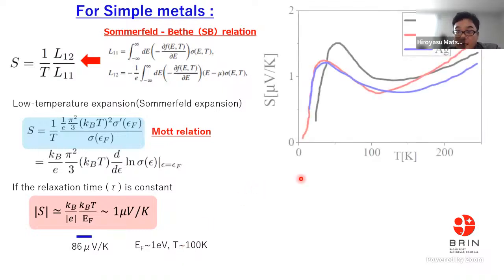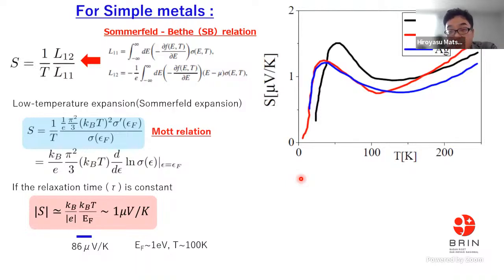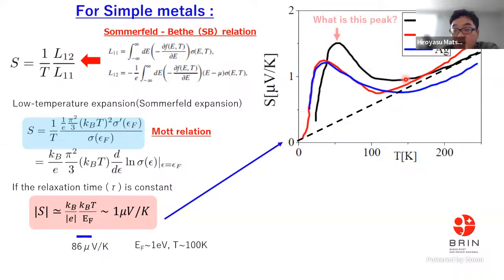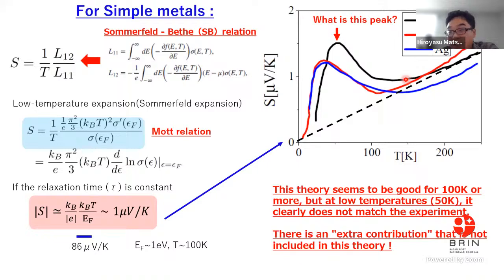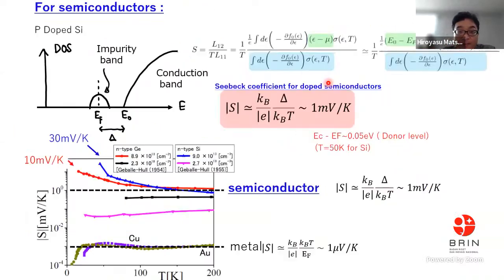So when we compare the experimental result, yesterday maybe I showed this experimental result. This is an experimental result of the copper, gold, silver case. Using this equation, we can draw these lines, but we have additional terms. So what is the origin of this additional term? Around here is okay. This is linear dependence, but we have the deviation from this equation. So we have an extra contribution in some effect.